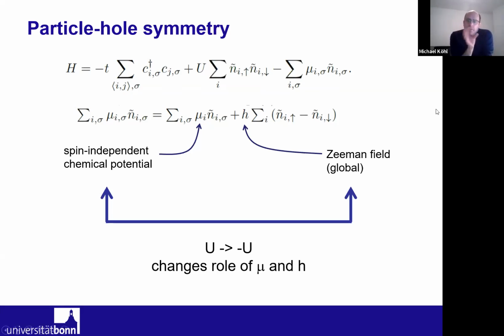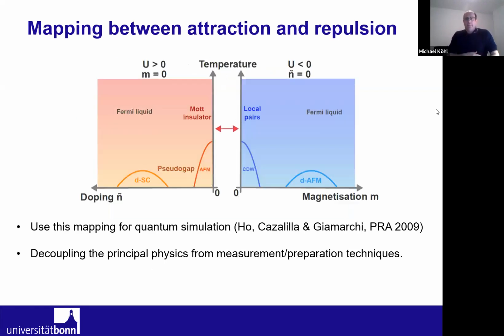So what we want to observe is that when we change the interactions from attractive to repulsive, all these phases map onto one another, but the chemical potential becomes the spin imbalance and vice versa. And Thierry Giamarchi and co-workers have worked this out very carefully already 10 years ago. And they actually show that every phase on the repulsive side, say for spin balance, but as a function of doping, has its matching correspondence for attractive interactions and magnetization now as the doping parameter, but for zero doping.